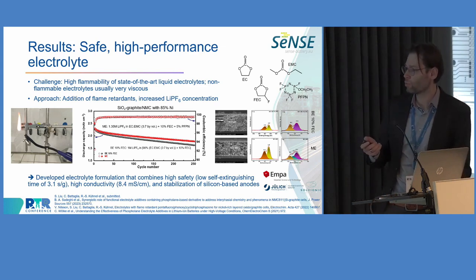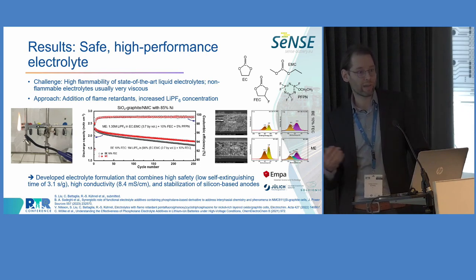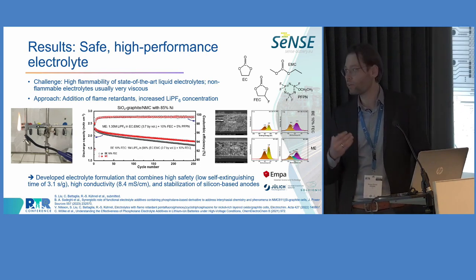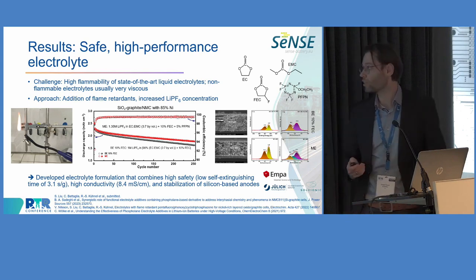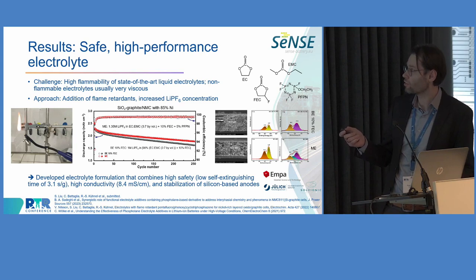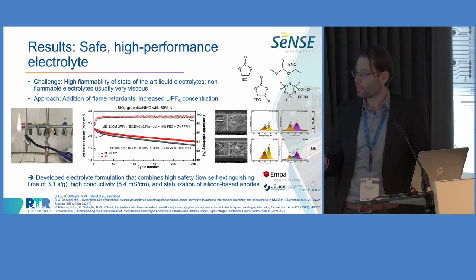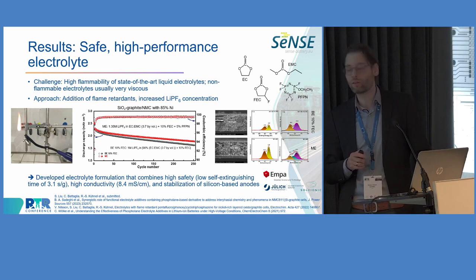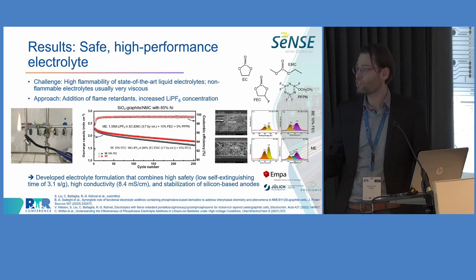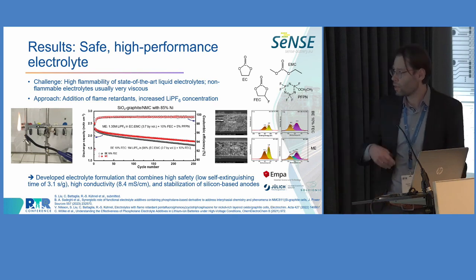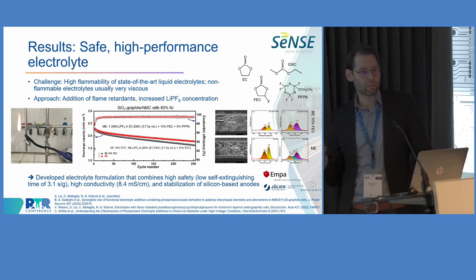So we explored multiple approaches in this project, and one approach that turned out to be quite successful is the use of flame retardants, because when we add flame retardants, we don't have to add that much, so the penalty in terms of conductivity is not that large as compared to some other approaches. And particularly this cyclotriphosphazene-based flame retardant is quite promising, because we just have to add 5% to really significantly reduce the flammability of the electrolyte when combining it with a higher lithium salt concentration. And there were even additional benefits that we found of using this flame retardant. It also improves the wetting properties of the electrolyte, so this compound wets Celgard separators very well instantaneously, basically.